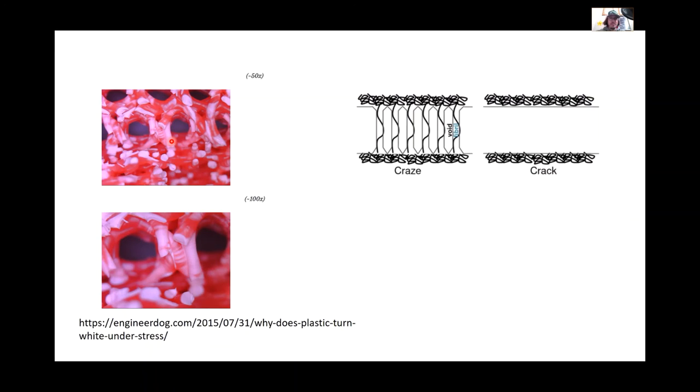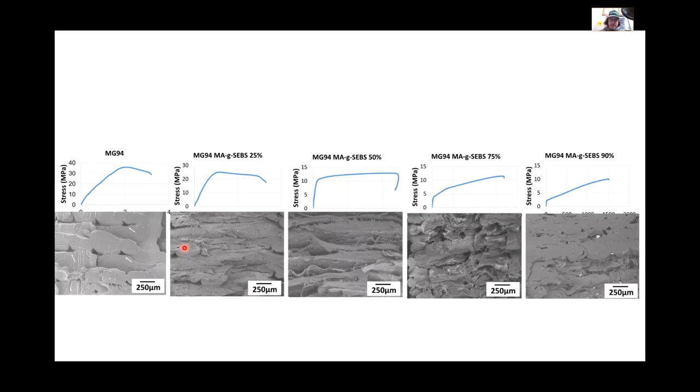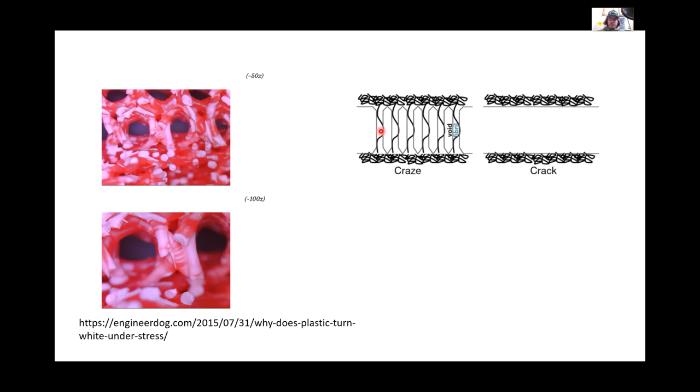And this craze actually exists because of strain whitening. There's a longer story associated with that. I may tell you at another time. But anyway, strain whitening is associated with craze cracking. Here's a schematic of the craze formation, and then it actually ruptures. So these chains will eventually break. There is some elongation going on of the polymer chain, so you get these microfibrils, if you will. These bigger fibrils, I tend to refer to them as macrofibrils. They're a little bit bigger than something on almost a molecular level, really, because it's an individual polymer chain that's stretching out.